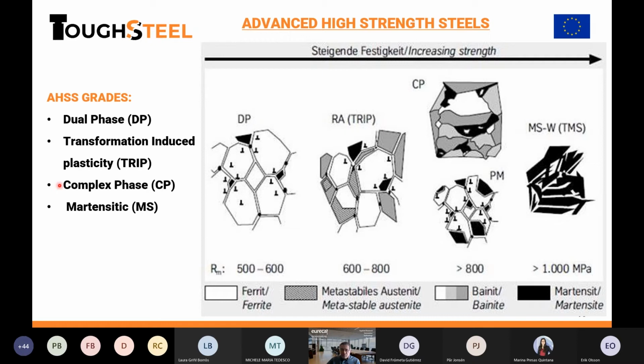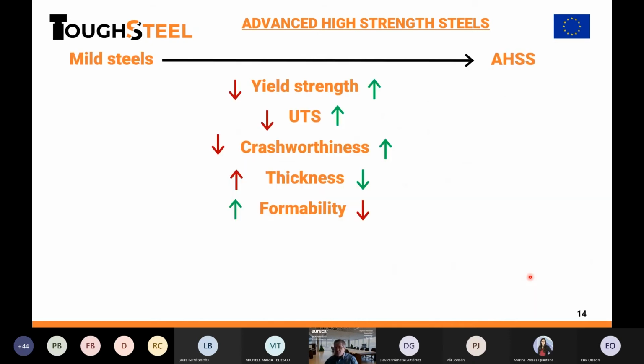The complex phase steels, as the name says, have a complex microstructure combining almost everything you can find in the steel: bainite, martensite, retained austenite, ferrite sometimes, carbides. And at the end of this progression of different phase assemblages between soft and hard phases, we have martensite with a higher strength and of course lower ductility. We will discuss these microstructures in terms of fracture toughness in the coming slides, so please keep this in mind, or at least if you check the presentation again, you can come back to this to compare what I'm going to tell you in the coming slides.